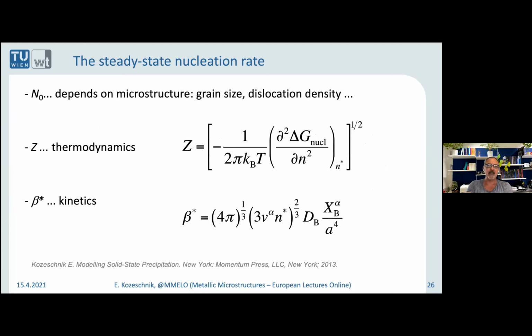For instance, N0 is the number of potential nucleation sites. Just keep in mind that I was showing you this tetrakaidecahedron and the different numbers in the table. So this is exactly where the microstructure enters in terms of the available sites. The Zeldovich factor Z is thermodynamic, and it's related to the second derivative of the nucleation energy at the barrier, so at the critical point.